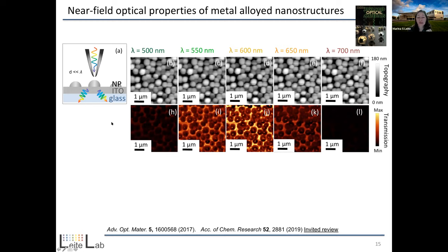So essentially, what this is telling us is the following. At 500 nanometers, it looks really dark, so a lot of the light is being absorbed. But at 600 nanometers, you can see that we have a very high field around the particle and also underneath it, I should say, not inside. These nanoscale measurements were in very good agreement with the macroscopic transmission measurements. You can see we have a peak in transmission around 600 nanometers, which translates very well with what's going on at the nanoscale.